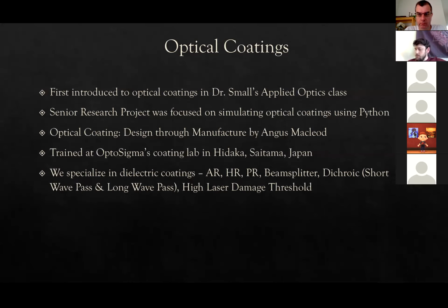And then with a lot of the higher end stuff, we'll use some kind of technology to compact the film, because essentially, SiO2 has a bulk refractive index of about 1.45, very similar to fused silica. But when you actually do this in the chamber, you don't get exactly that, because you don't get the same packing density as a real film. So you end up with a slight difference in refractive index, but you can get it to about 95% of the refractive index that it should be by using a technology called IAD, which is ion assisted deposition, and it sends ionized particles to compact the film while you're coating at the same time.